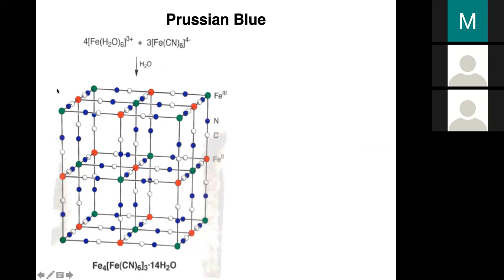And so in the product that you get, this is just the unit cell. It's a face-centered cubic unit cell again. The red spheres are iron 3+, and the green spheres are iron 2. The carbon end of cyanide is bound to iron 2, whereas the nitrogen end of cyanide is bound to iron 3. Both metal centers have an octahedral coordination geometry. But of course, the carbon end of cyanide has a slightly different ligand field from the nitrogen end. In particular, it has a much greater overlap of the pi star orbital of the ligand with the metal, so a slightly stronger ligand field around the iron 2 as a result.